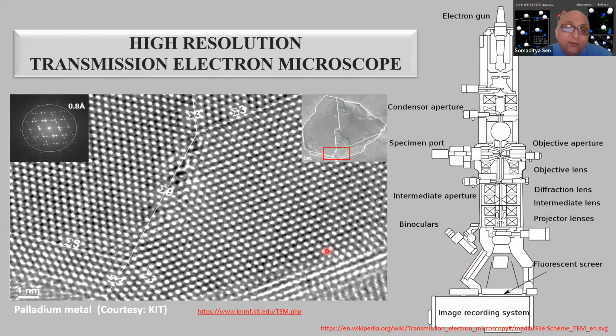And what we can find, this is an ideal example I keep on taking. You can see there is a crystallite here, a big crystallite, and then there's another big crystallite with thousands of atoms arranged properly in this domain. And then there is another region where the domain has changed here. So the orientation has changed. It is part of the same crystallite particle, but it is a different crystallite. There is a difference of the domains that are available. So all these are types of crystallographic defects.